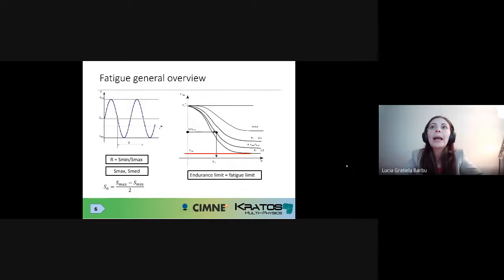An important concept also to understand is that the Wöhler curves tend, as we accumulate the number of cycles for very high fatigue lives, millions of cycles, to an asymptotic behavior for most metallic materials, not so for aluminum alloys, okay? But most metals exhibit this type of asymptotic behavior with large lives, millions of cycles. And the stress level associated to this asymptotic line is the endurance limit, or what is very commonly known as the fatigue limit.